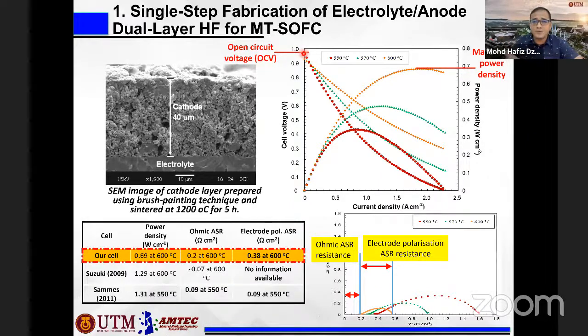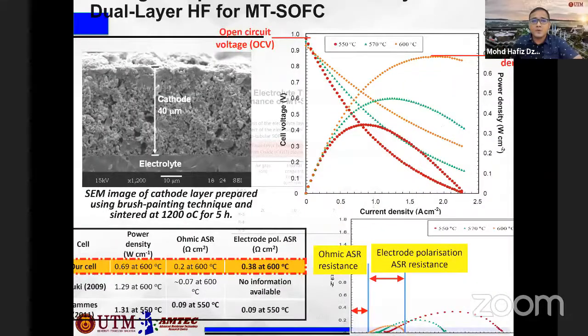The theoretical OCV, open circuit voltage, for the fuel cell is 1.1 based on the Nernst equation. But what we got here is almost 1, meaning that the electrolyte that we produced is quite dense. Okay, so if we look here, the power density that we produced at the highest temperature, 600, is 0.69 watt per centimeter square. This, if we compare with the literature, is still quite low. So we try to find an alternative to further increase the power density of the fuel cell, because the higher the power density, the better the performance of the fuel cell. So we try to reduce the thickness of the electrolyte.